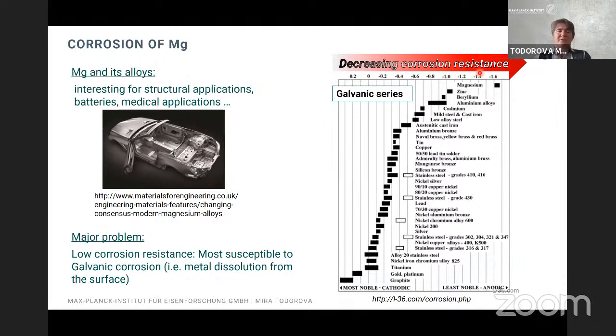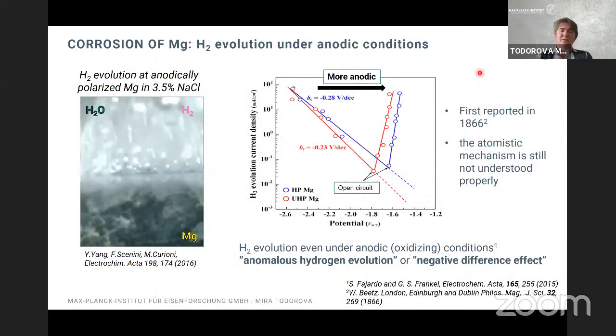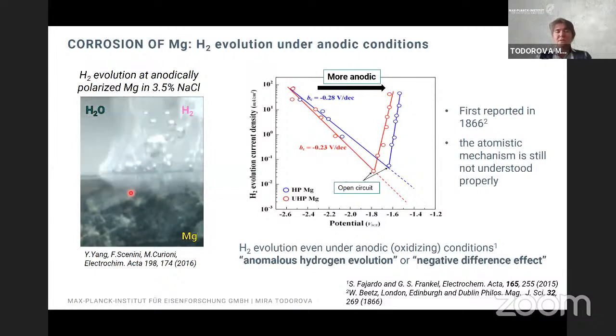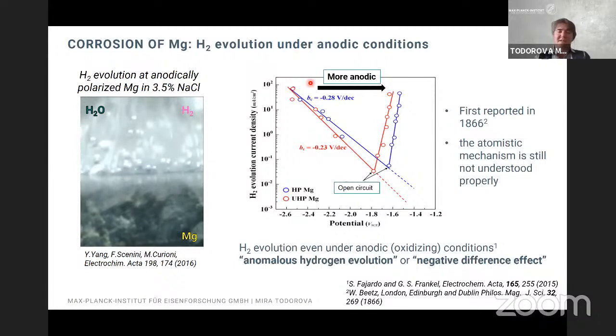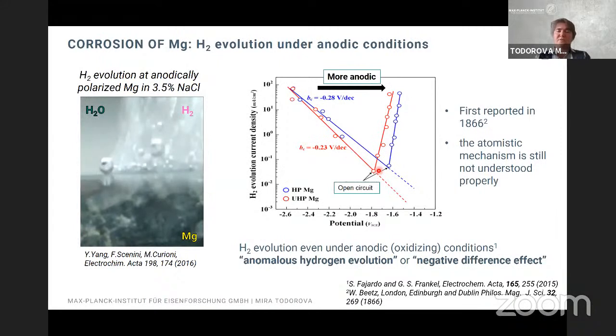There is also a very peculiar observation regarding the corrosion of magnesium, that there is a really very violent hydrogen evolution at anodic conditions. Anodic condition means that we have a positively polarized metal surface, and hydrogen evolution is usually a reaction that is associated with cathodic conditions. But these measurements show that, while initially there is a decrease in the hydrogen evolution current density as we go more anodic, there is a reversal of the behavior.